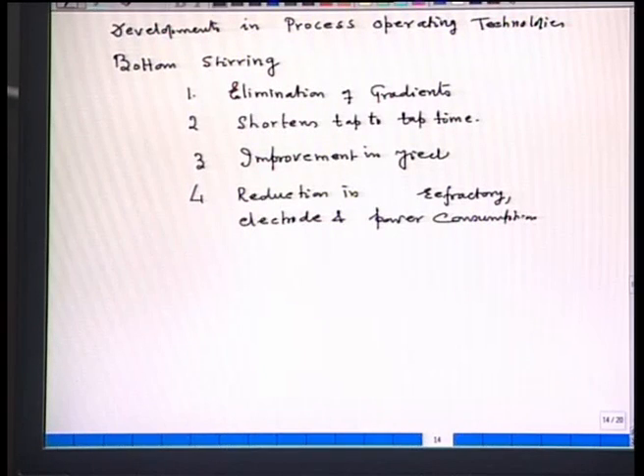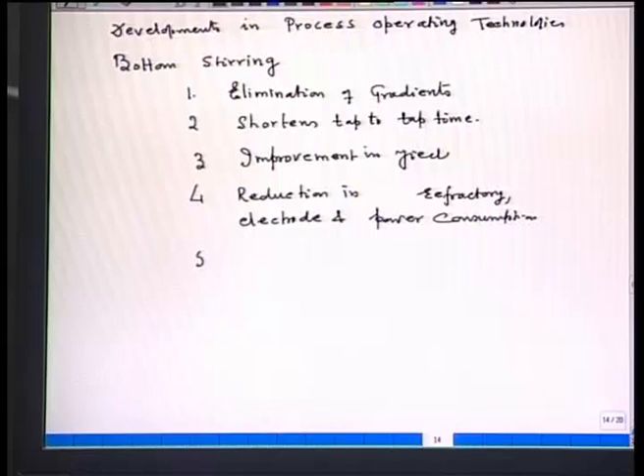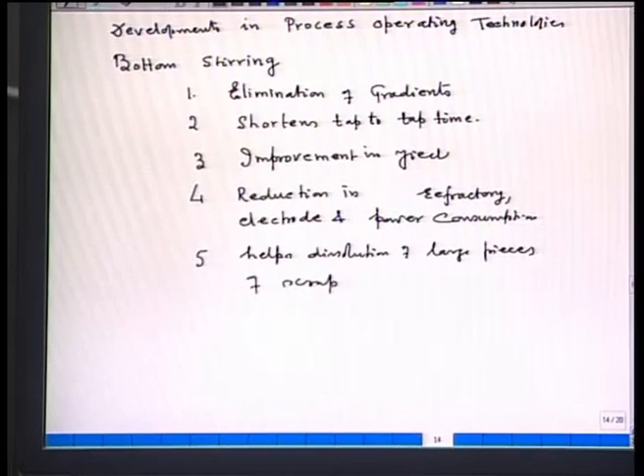Now, this advantage is coming because of shortening of tap to tap time. When you shorten the tap to tap time, naturally the electrodes are exposed for a lesser amount of time. The one particular heat is exposed also for a short time with the refractory, and hence all these things will follow. Another important advantage of bottom stirring, it helps dissolution of large pieces of scrap, because now the stirring conditions are good. So, the scrap can be dissolved a little bit faster.